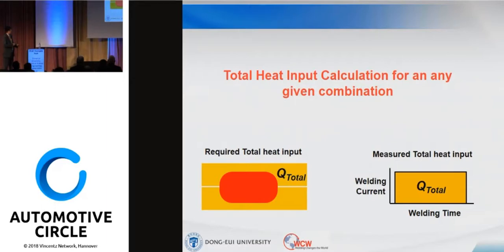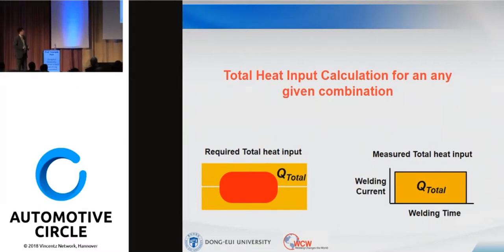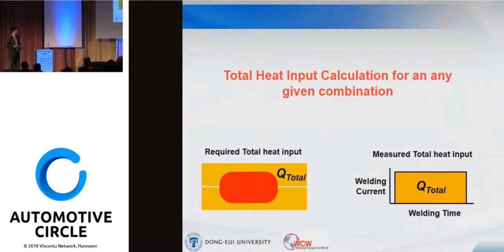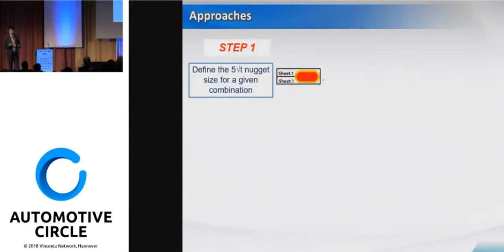What you can do is, for any given combination with a similar combination, you can actually calculate the required total heat input for the target of a certain nugget diameter. At the same time, you can actually measure the heat input during the actual welding. So the calculated total heat input and the measured total heat input should be approximately similar. Here's my approach. Step one. Let's define the 5√t nugget diameter for a given combination. So 5√t should be a large enough nugget diameter for guaranteed welding quality.